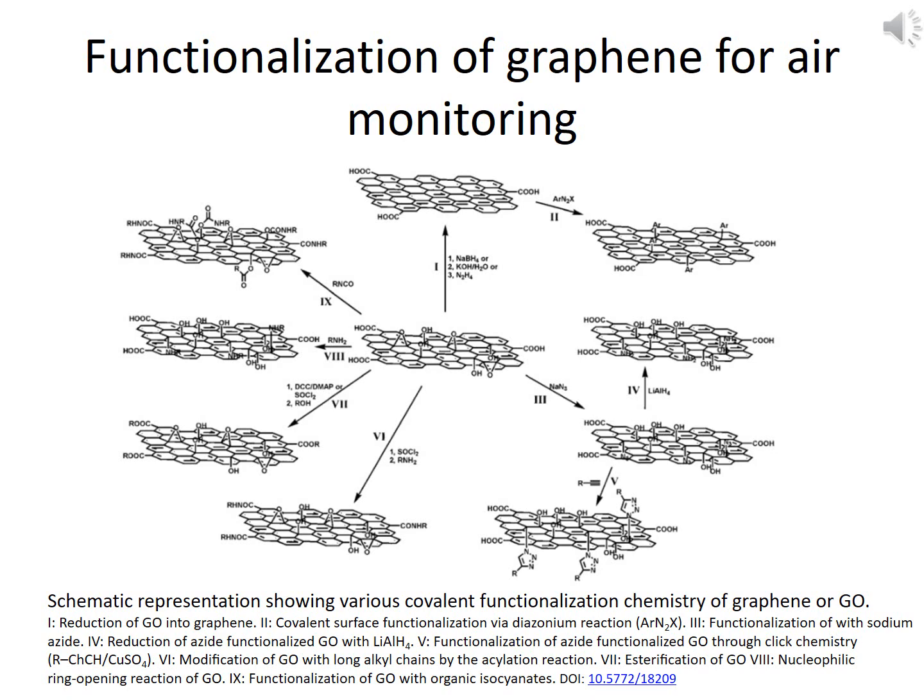Surface modification of graphene can be achieved by various forms. Chemical functionalization of graphene can be of covalent nature, as shown in the slide schematics, or non-covalent. The structural alteration of covalent functionalization can occur at the end of the sheet and or on the surface. Surface functionalization is associated with rehybridization of one or more sp2 carbon atoms of the carbon network into the sp3 configuration, accompanied by simultaneous loss of electronic conjugation.